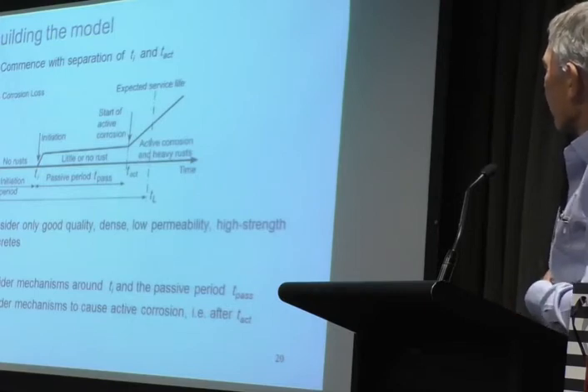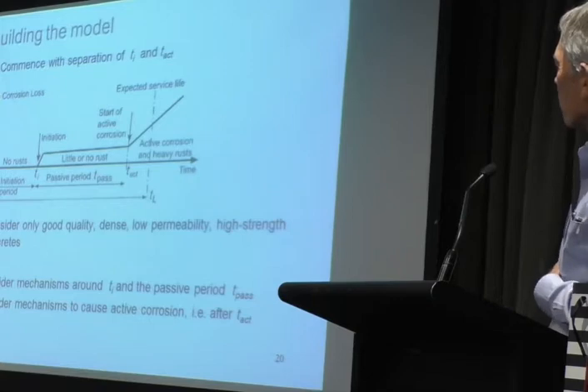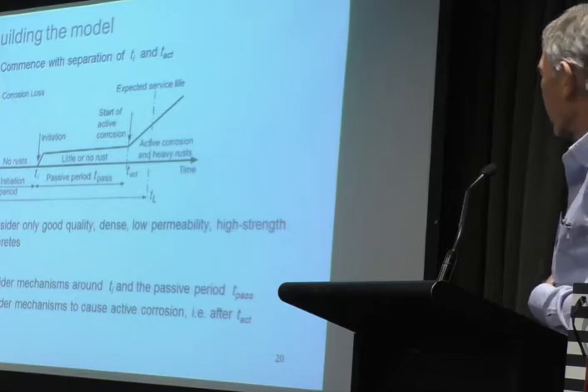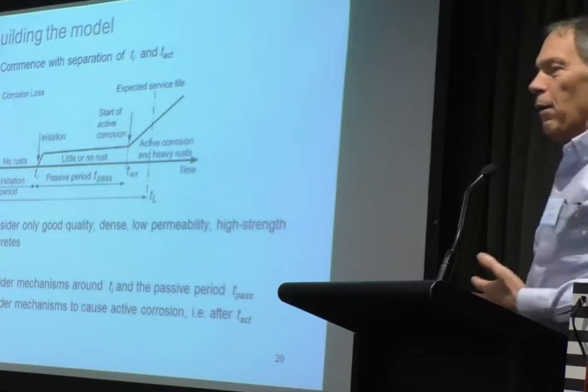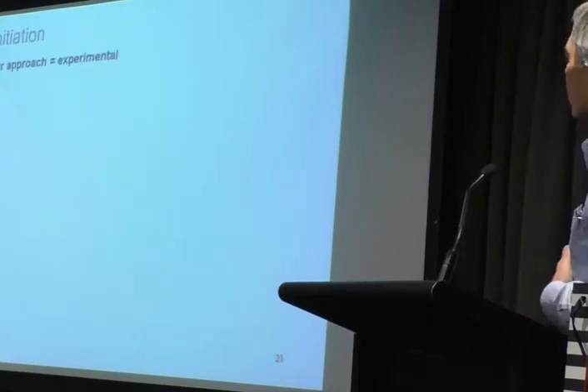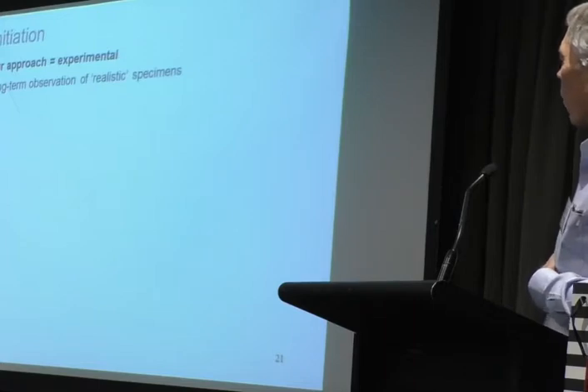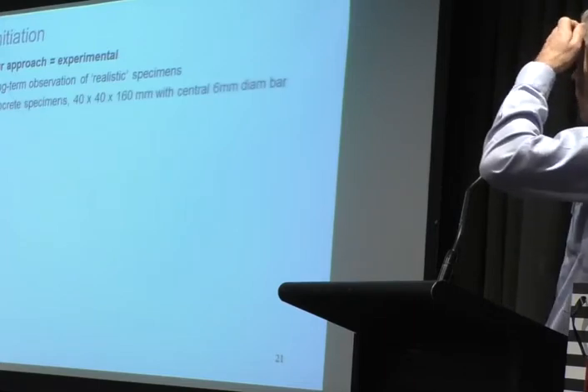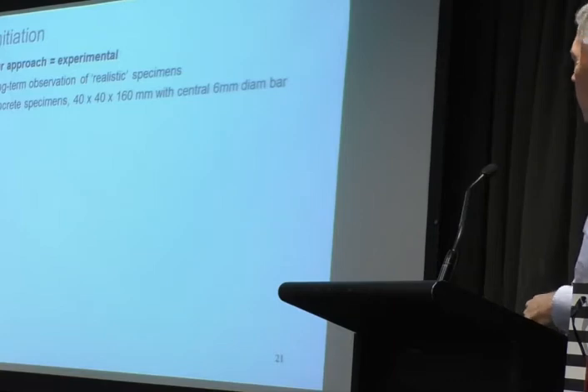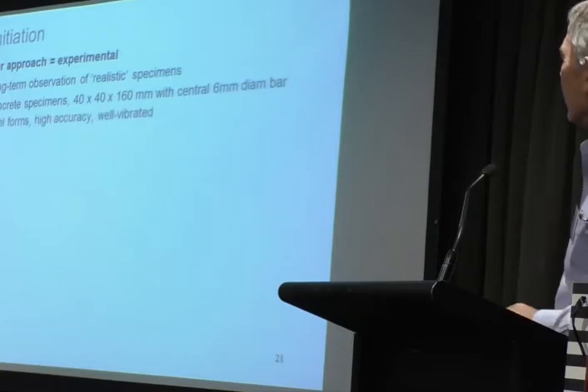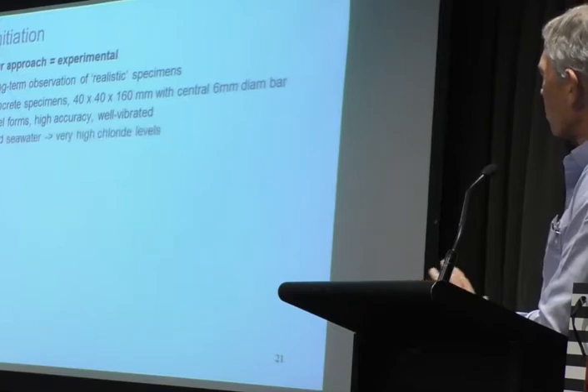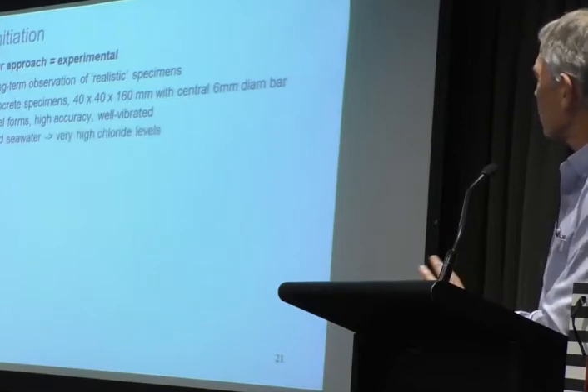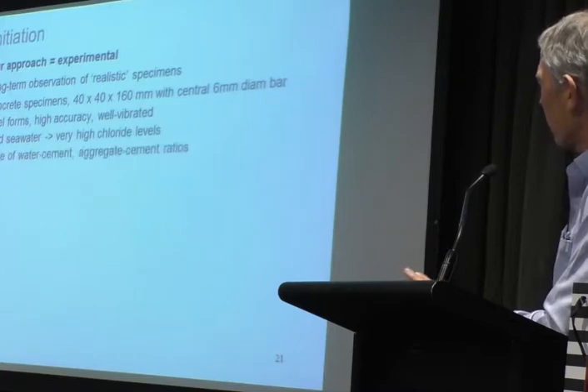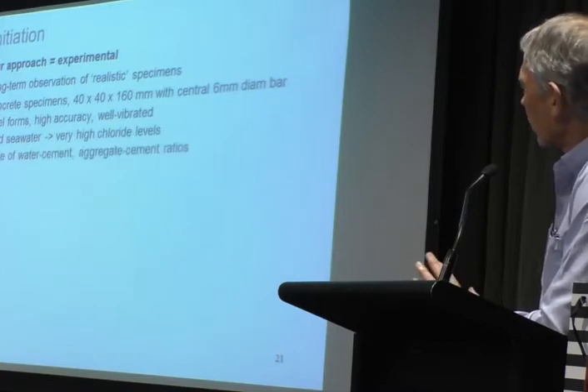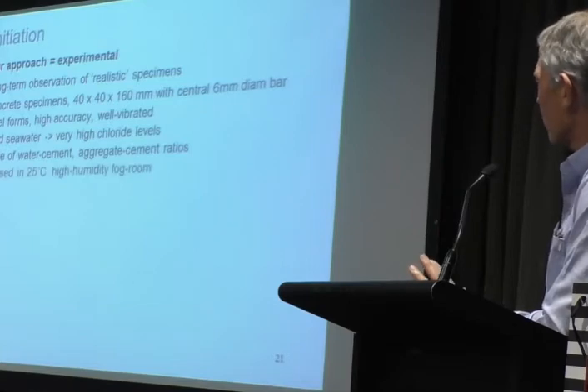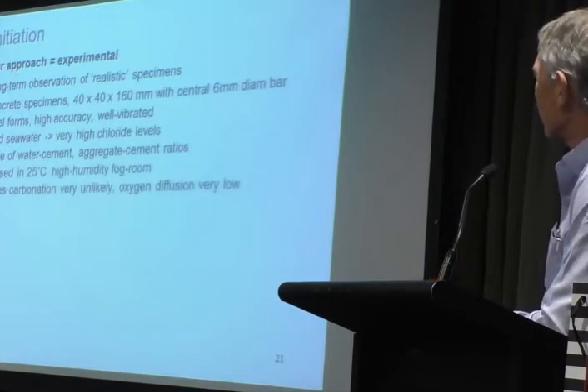So coming back to this now, what can we say about the initiation bit and the active corrosion time? I want to really focus on those. We need to think about what's going on in those periods of time. So initiation, our approach is experimental. We did a long-term experiment where we had very small specimens, 40 by 40 by 160 millimetres with a central bar. We put them in high accuracy steel forms. They were all made exactly the same way. We used seawater to start them off. Range of water cement contents, aggregate cement ratios, fog room, all that sort of stuff.